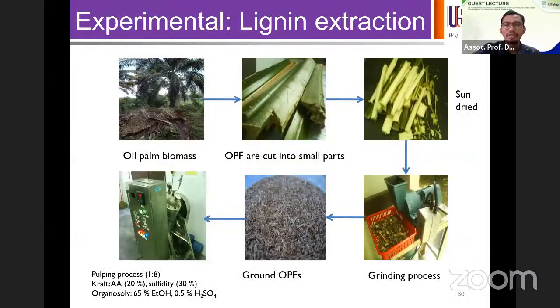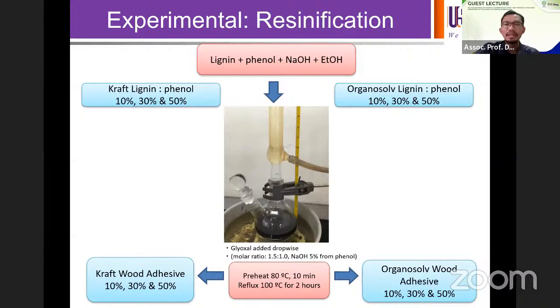Again, in order to get the polyphenols, we have to extract the lignin from the biomass. After the lignin extraction, we do the resinification process. We include different percentages of lignin substitution, and we also include glyoxal as the less toxic aldehyde with a fixed molar ratio. Over here, we also did the study with different types of lignin. We have kraft lignin and organosolv lignin. We want to study which type of lignin performs better.